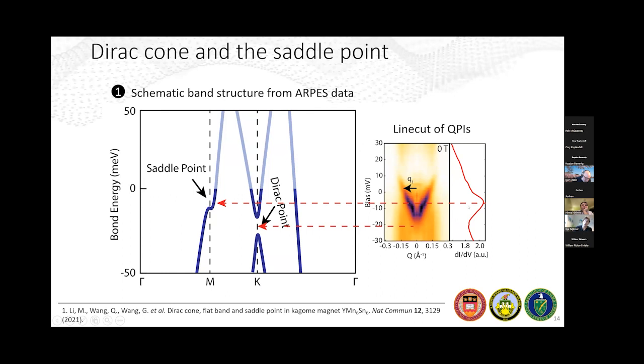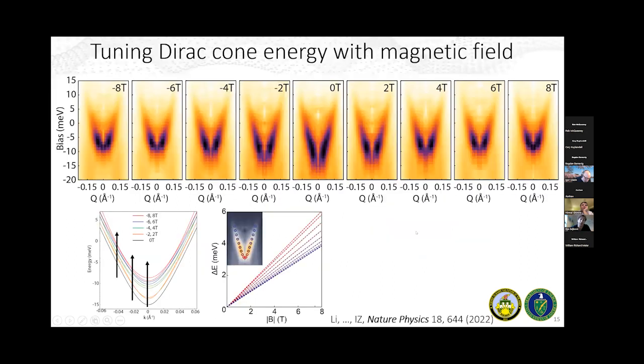To infer what this is coming from, we compare to the calculations in comparison to ARPES. Based on the dispersion velocity that we see here and based on the energy, we attributed this dispersion to the Dirac dispersion right there. And this peak here, which occurs maybe 5 millivolts below the bottom of this Dirac cone, is likely the saddle. So this is the identification of the spectral features.